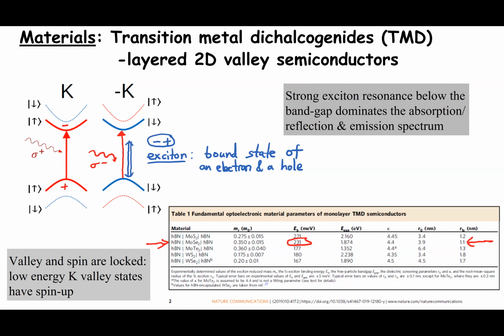This is a nice table put together by Scott Cooper for different semiconducting materials. The one that is of interest for us is molybdenum diselenide. The binding energy of the exciton is 230 millielectron volts when it's encapsulated in hBN. Without hBN, it is believed that it would be about 500 millielectron volts, but there's no measurement, for example at high magnetic fields, that will allow you to determine this, at least not easily. And the Bohr radius is 1.1 nanometers. So you can see that the electron and hole correlation is not at the underlying lattice length scale, which is about 3.5 angstroms or so. But the electron and hole delocalize over, let's say, 10 lattice sizes.